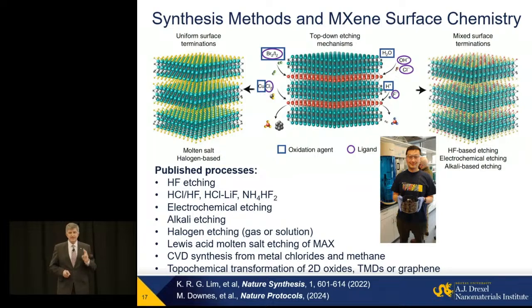But to make a difference, we need to be able to make materials in quantity. And we take ceramic powder, basically MAX phase, put it into etchant, whether it's liquid etchant or in a reactor and run gas by, or molten salt. It's really the size of the reactor that determines how much we make.